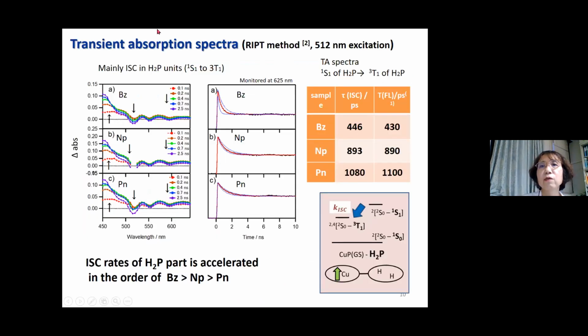On the other hand, we excited our free base part selectively, and we can observe intersystem crossing within the free base. Here we see the time dependence of the transient absorption spectra. This expresses the transient absorption change from the singlet state absorption to the triplet absorption of the free base part. From here, we can also calculate the intersystem crossing rate of the three dimers, and this rate is 400 picoseconds, approximately 900 picoseconds, and 1000 picoseconds.